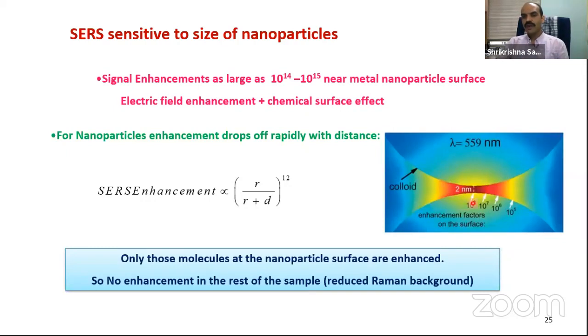But if you go away from this metal surface, or metal nanoparticle surface, it is decaying very fast. It is going from 10 raised to 8 to 10 raised to 5. What does this mean? It means that if you go away from these nanoparticles, the intensity of the Raman peak will decrease, and therefore this particular region is called the hot spot. Now, what do you mean by this hot spot? The hot spots are very close to the metal nanoparticle surface.